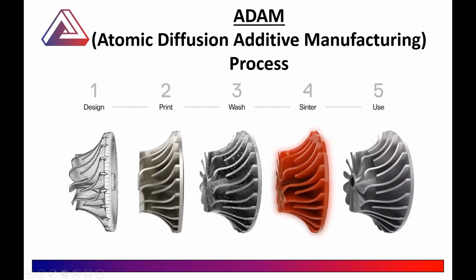The process is quite simple and straightforward. Obviously, start with your design. How suitable is it for 3D printing? You carry out the 3D printing, which is relatively straightforward. It's very much in a traditional looking FFM printer, and nothing special. At this point, once it's printed, we weigh it, and then we put it into a wash. What we're trying to do through the wash is start to break up some of the wax and plastic in the print.